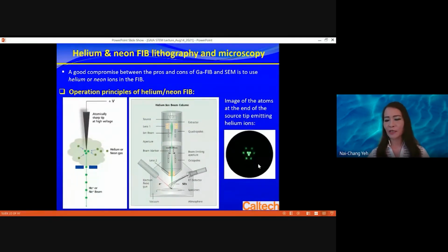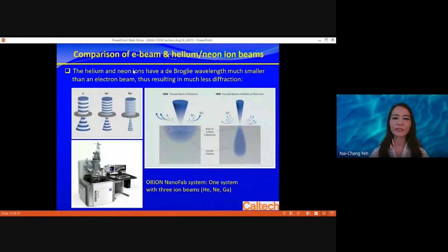So this is an image of what the helium ions, the helium probe, actually look like. It's only a few angstroms, so it has very high resolution. This is a picture schematically showing that with an electron beam, the de Broglie wavelength is longer, so you have larger diffraction and the resolution is a little less. With a helium or neon ion beam, the masses are bigger than electrons, so the diffraction is smaller, and you can have good resolution without causing a lot of damage.